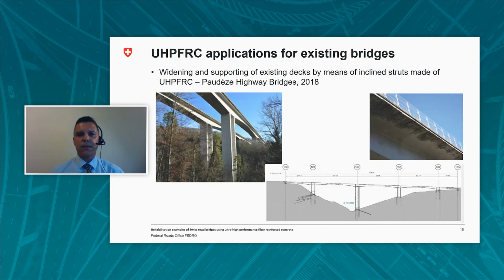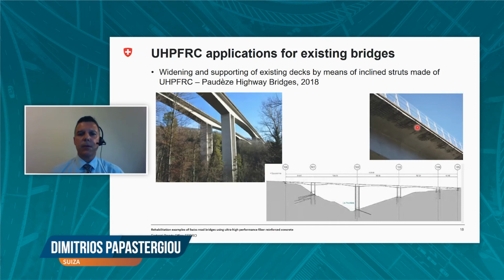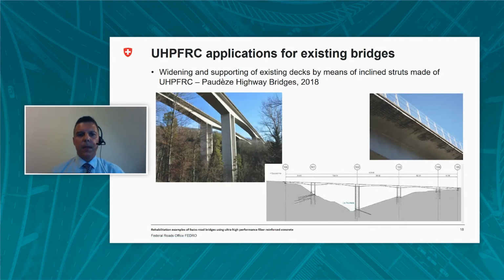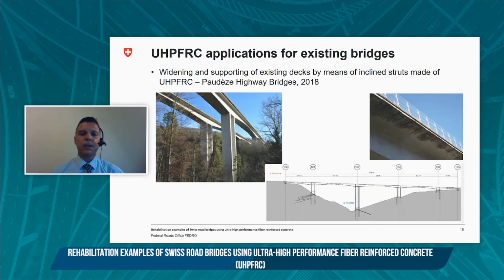The latest inspections have revealed several damages. More precisely, concerning the slab, the cantilevers were found to be in poor condition, with spalled concrete and corroded steel reinforcement on all edges. Furthermore, future requirements for diverting the traffic during important rehabilitation work on the highway necessitated widening of the deck. Any possible intervention had also to take into account the replacement of the curbs by concrete crash barrier walls for enhanced security against lateral shock.